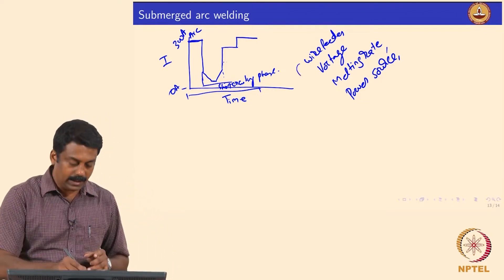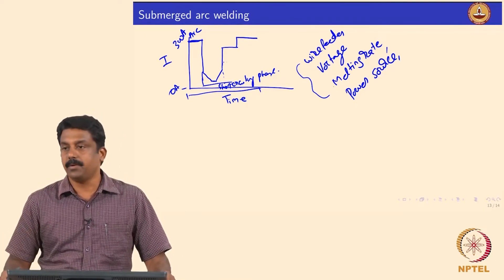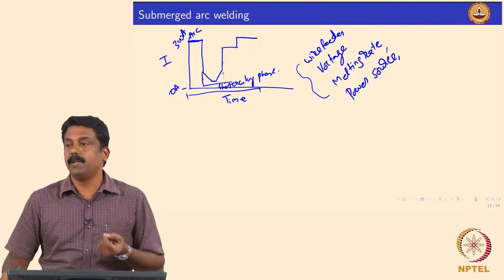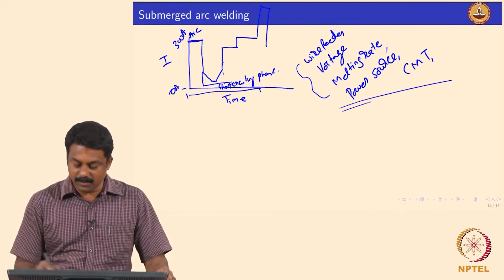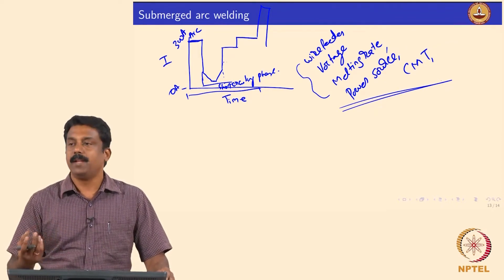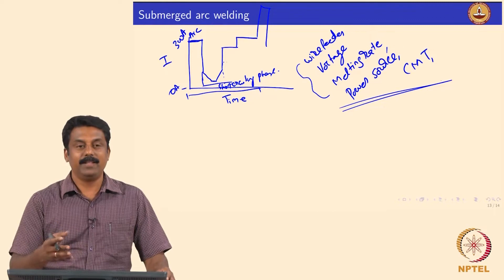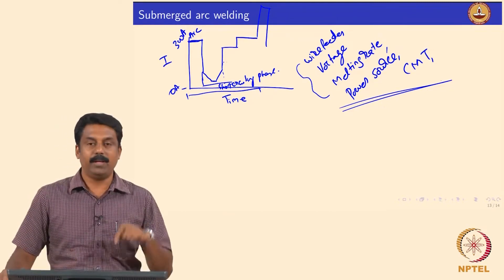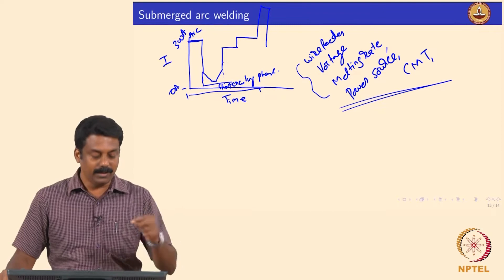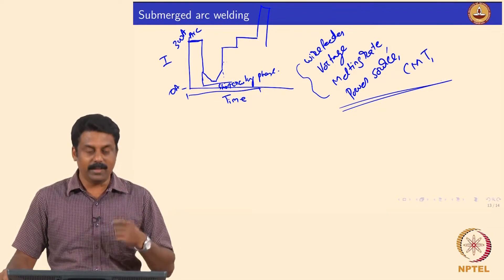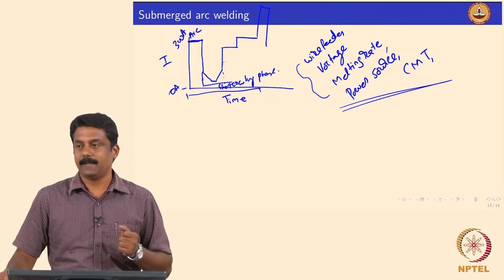Once you achieve this, using online sensors we can measure voltages, calculate melting rate using the equations, and develop an individual welding program for a given wire composition and diameter. These advantages are possible because of the advancement in understanding the physics of the welding process. Once you know what is happening during welding, you can adjust accordingly. When short-circuiting occurs you cannot just let it short-circuit - it will explode and the weld pool will collapse. We have to manually adjust current and voltage waveforms, identify the effect on short-circuiting, and then program it to be automated.